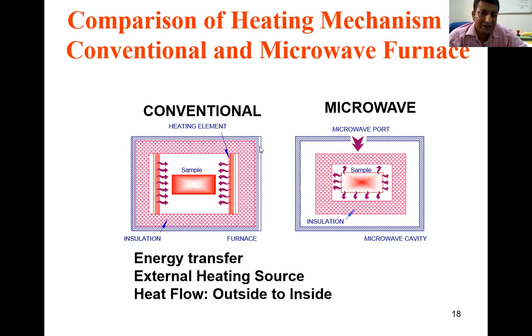Here we can appreciate heat is coming from the heating elements. This is our sample specimen, and heat comes from outside and to the inside. So there is, as I was talking about, a thermal gradient. At the top the temperature will be more, and inside the temperature will be less. But in the case of microwave heating,